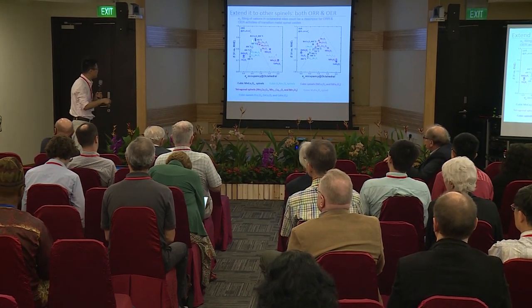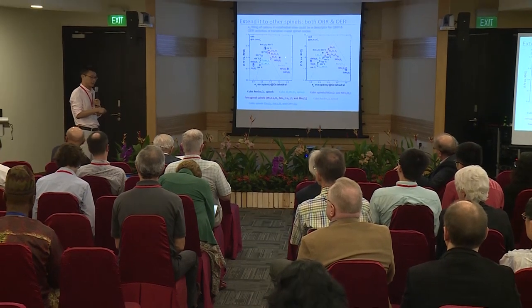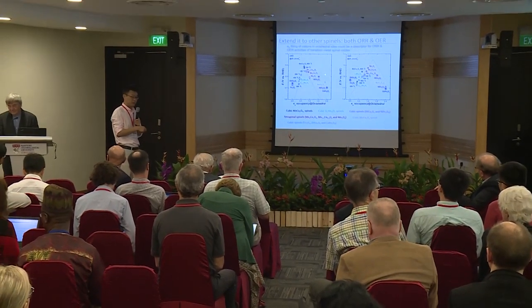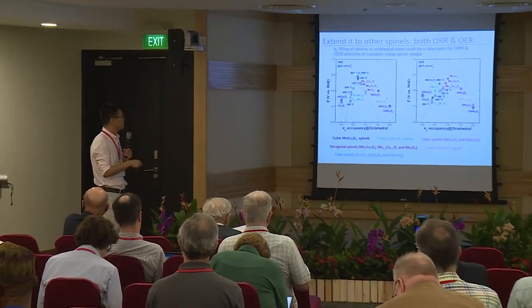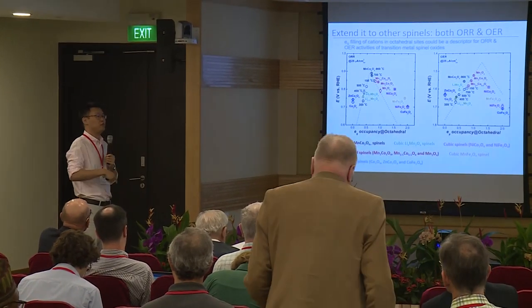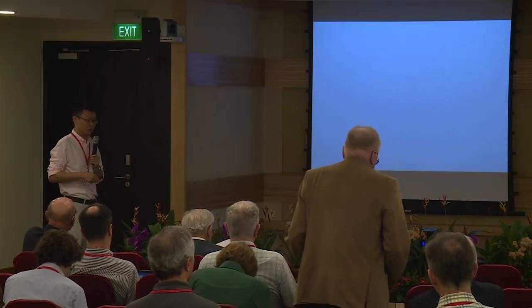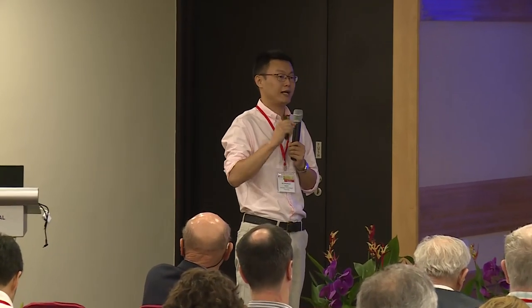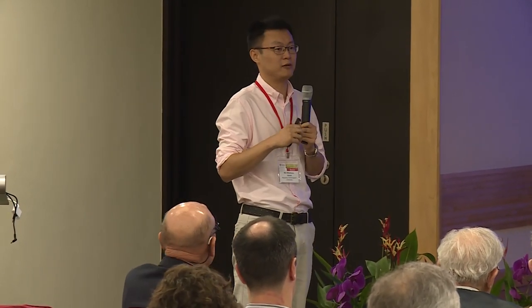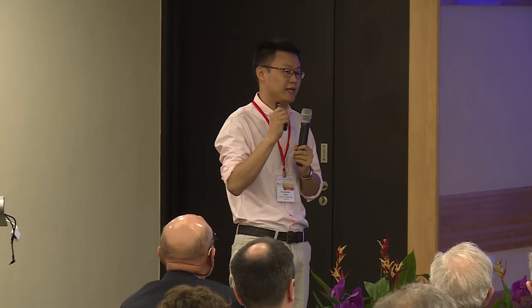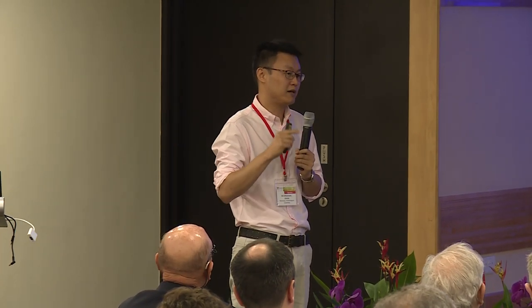Yes, this is a good question. 25 microampere works. If you go to 50 microampere, it also works. If you go to 100 microampere, it also works. But if you go to 1 milliampere, probably it does not work well, especially for the OER. At high current density, you must be careful. Current density is normalized by oxide surface area, not the electrode surface area, so it's really hard to reach 1 milliampere per oxide surface area. If you go to that region, the overpotential is really high.